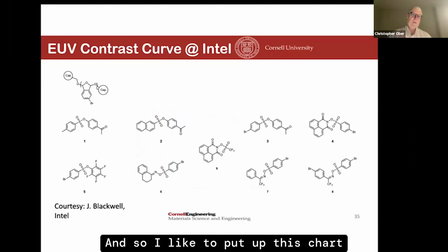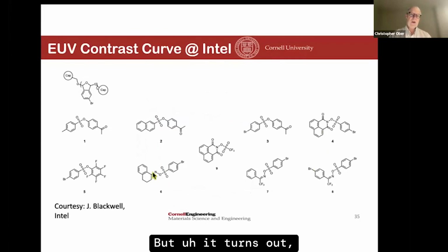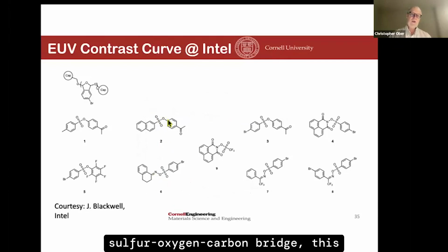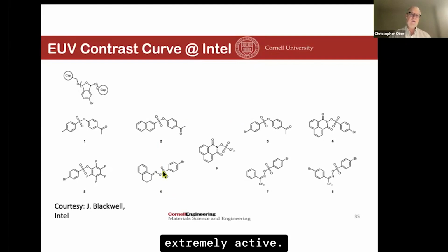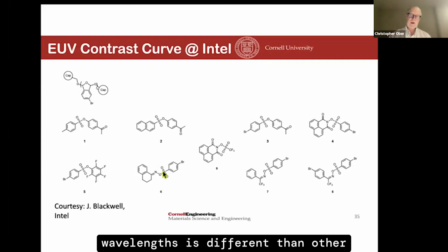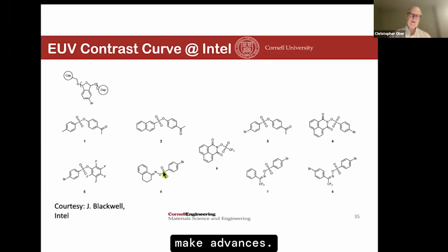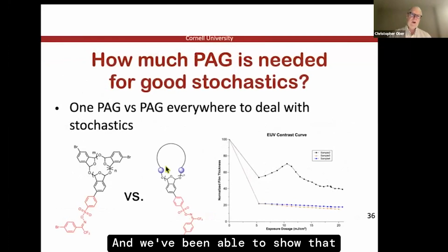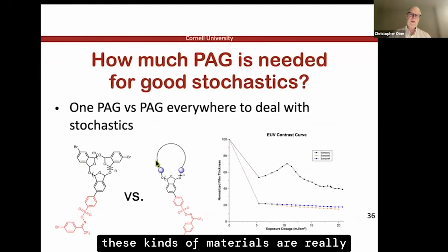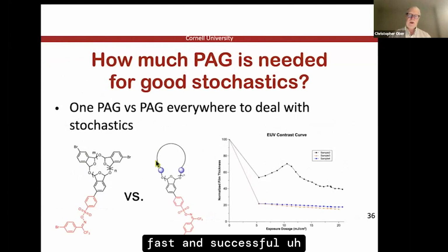And so I like to put up this chart and ask people, what's the difference between these different non-ionic photoacid generators? But it turns out that if you have a sulfur oxygen carbon bridge, this is dead at EUV wavelengths. But if you have a nitrogen oxygen sulfur bridge, it's extremely active. And so my conclusion is the photochemistry under EUV wavelengths is different than other patterning methods, and we still don't completely understand that. Nevertheless, empirically, we can make advances, and we've been able to show that these kinds of materials are really fast and successful photoresists.